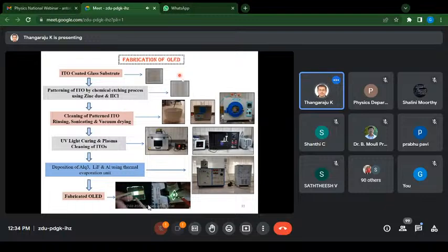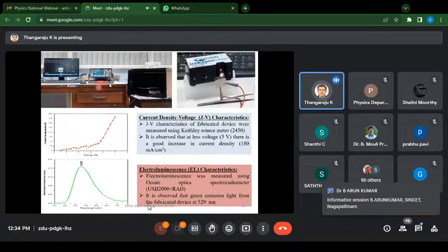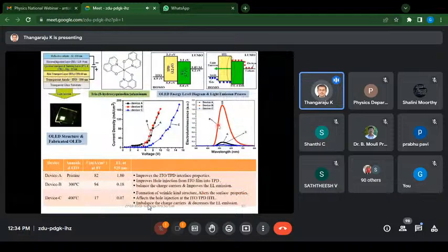You can see that the LEDs are fabricated in our lab. You can see that the LED fabricated in our lab is glowing and it is being characterized. For the characterization facilities, we have a source meter and a spectroradiometer. We have also made a device based on Alq3 material, and we studied that annealing of the indium tin oxide anode improves the device efficiency. This is published in a paper published by the AIP.